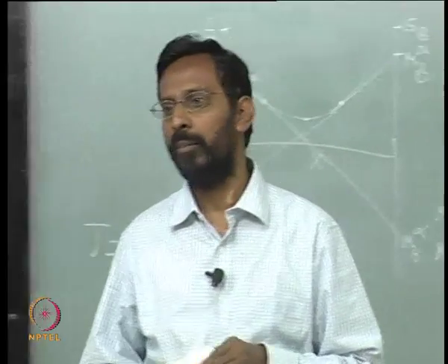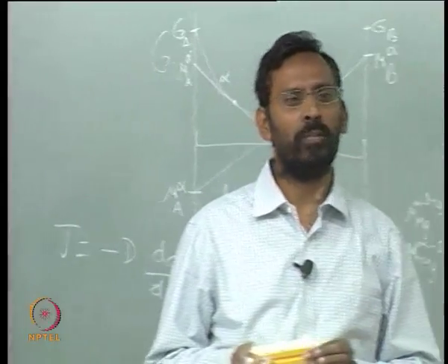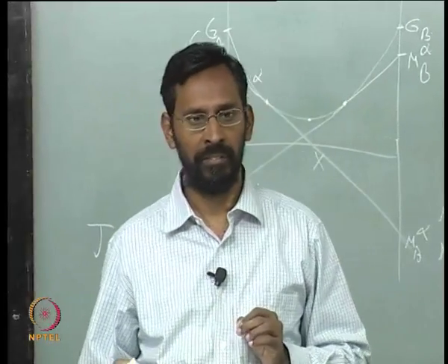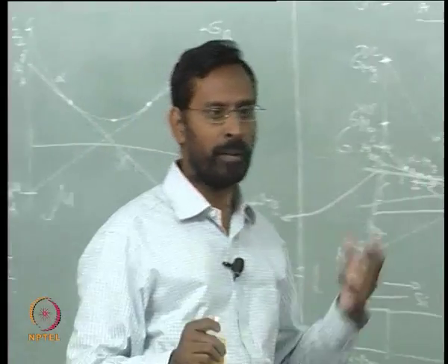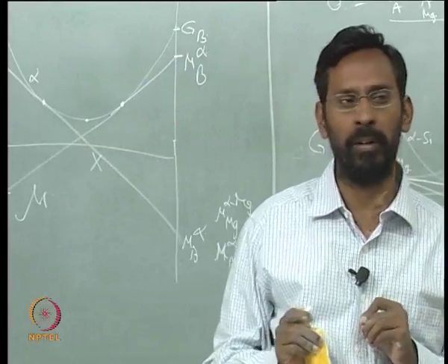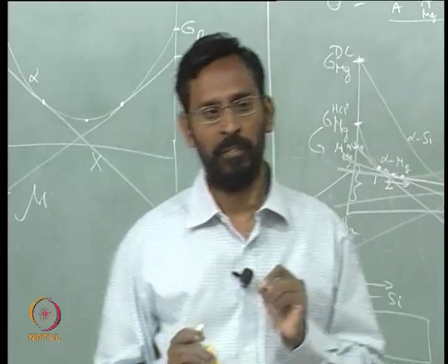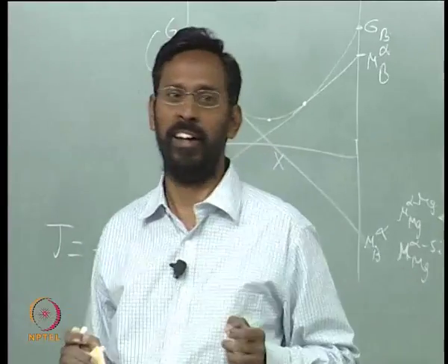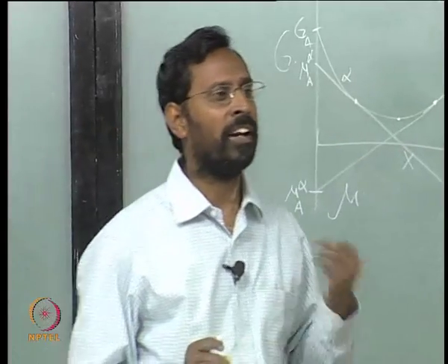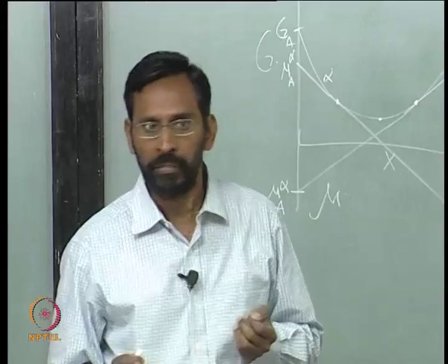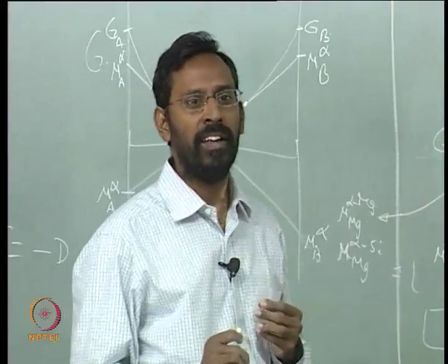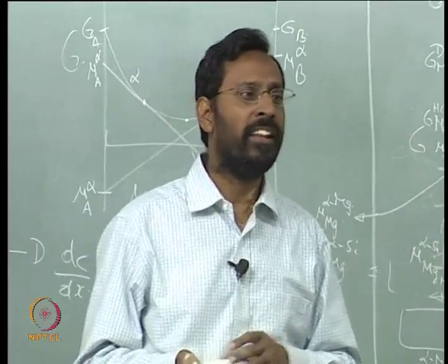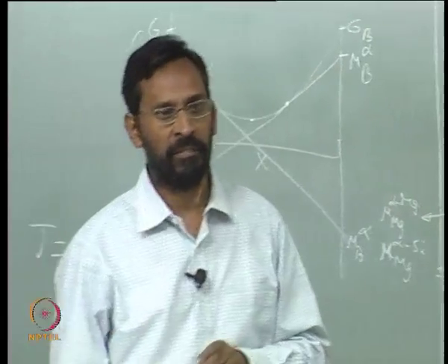What do you expect when these two are kept at high temperature? You expect that the carbon should diffuse from the cast iron side to the steel side, isn't it? One side is 3% carbon, another side is 0.4% carbon. You actually see the reverse. Carbon will go from the steel side to the cast iron side. People started calling this uphill diffusion, and the reason is, though the concentration gradient is there, there is no chemical potential gradient.